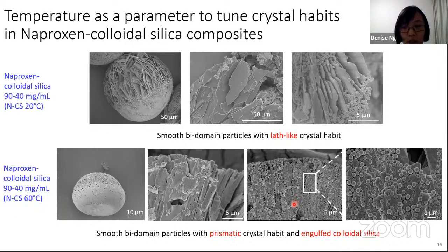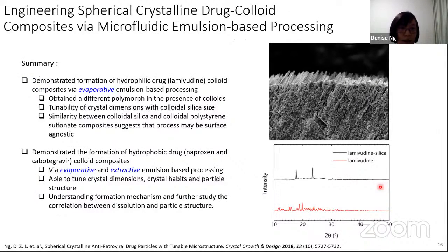And on the colloid-rich region, a significant difference was also observed. So here we have thin leaf-like crystals that are dispersed among colloidal silica, whereas here we have prismatic crystals that have colloidal silica actually being engulfed inside the crystals itself. So with this, we have briefly demonstrated that we are able to form hydrophilic drug-colloid composites in the case of lamivudine via evaporative emulsion-based processing.